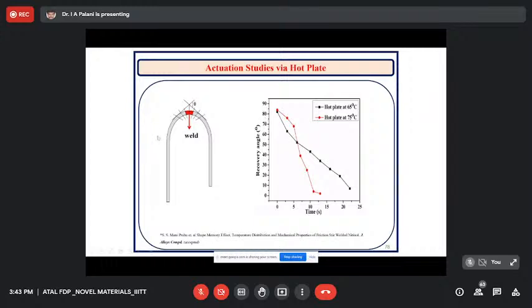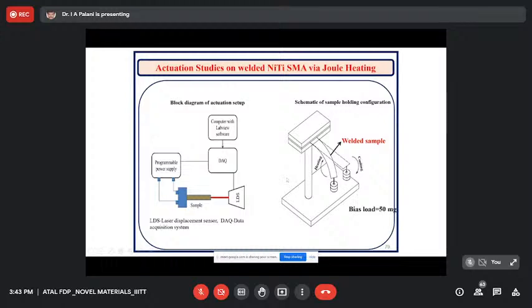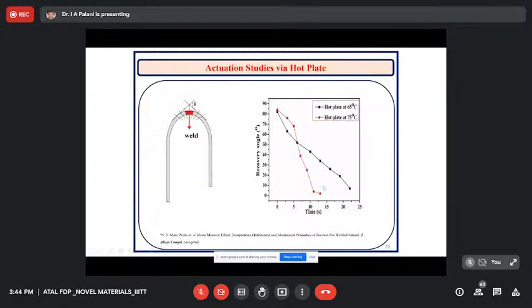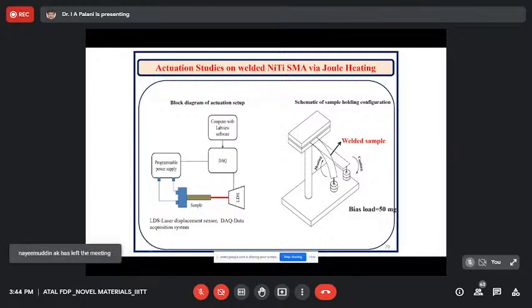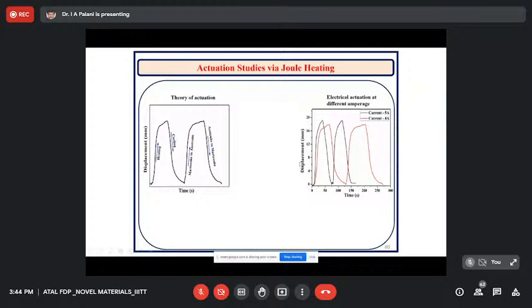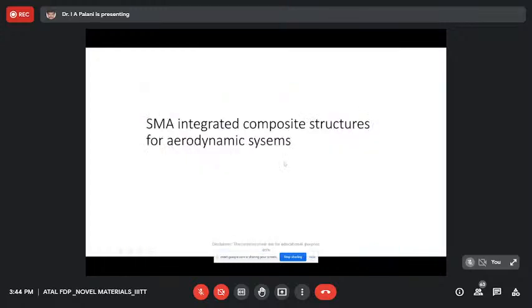In order to study the recovery angle, we made an arrangement something like this. In this arrangement, we applied a load to it, and then we apply heat to it to get the actuation behavior. Using a DAQ, we were trying to harvest the data. This is the theory of actuation which we have employed, one with respect to displacement and one with respect to time. We were trying to study the heating and cooling characteristics, basically the martensite to austenite and the austenite to martensite behavior. We were also interested in studying the electrical actuation at different amperage conditions.